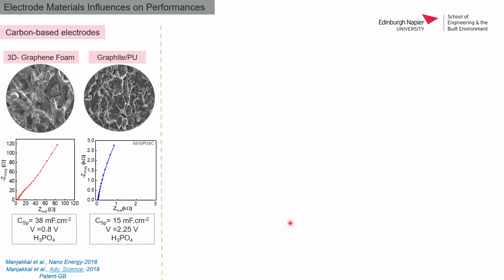So in my work, what I noticed is that it depends on the type of the electrode. For example, I developed a carbon-based electrode, a 2D material, a 3D structured graphene foam, and a graphite polyurethane composite based electrode material for my device. Depending on the type of the electrode which I used, the operating voltage and the electrolyte, the performance varied.